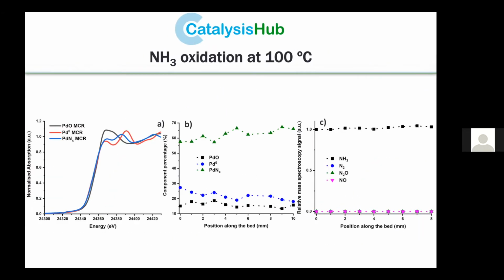As we increase the temperature, to enhance the information obtainable from the XANES, we applied multivariate curve resolution, which allows us to obtain the discrete components of the spectra. The MCR method is particularly powerful in separating and identifying the evolving species within a large data set. We were able to find three spectral components in the XANES spectrum: one which can be ascribed to palladium oxide, one to palladium metal, and the other to palladium nitride.